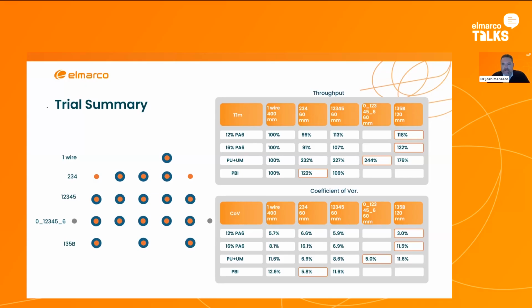This is what we're looking for, is to get more fiber spinning. But in the case of this polyurethane system, it's the PU plus UM. You can see that we more than doubled the throughput by putting the wires closer together, so we could fit more wires in the same space and not impact, and still get a lot of throughput from each individual wire themselves. But whereas nylon, you put them closer together, you don't really get any increase in the overall throughput for the number of wires you have.